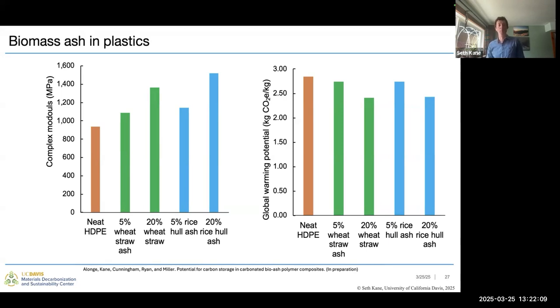And then we also see about a 5% and 20% reduction in the global warming potential of that plastic as a result of replacing primary plastic with these waste ashes that might have relatively little greenhouse gas emissions associated with them. In this case, we are just showing the CO2 treated ashes in the plastic because there is not that actual chemical interaction. We see basically identical performance mechanically between the treated and untreated with CO2 ashes. And so you can squeeze out a little bit extra benefit here by treating those ashes with carbon dioxide, whereas in the concrete, we do see that reduction in mechanical performance.